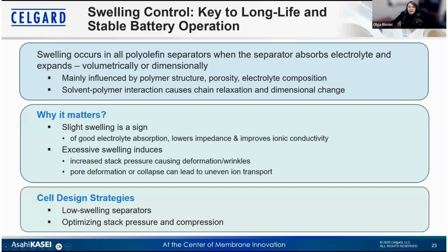There are several design strategies that cell designers can employ to counteract this type of behavior. Some of them are optimizing your electrode structure, but also optimizing the stack pressure and the compression. But on the other hand, in terms of separator selection, there are also low swelling separators that can help immensely to reduce this issue.